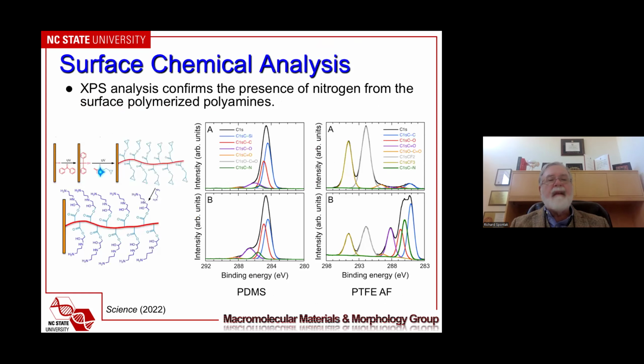This is the chemistry. I don't have a whole lot of time to go through this, but suffice it to say that it starts off with hydrogen abstraction, and then we start to grow polymer chains off of these embedded monomers. And once the polymer chains are grown, we can do a little bit of substitution chemistry to introduce the amine groups. And these are the XPS spectra to prove that, yes, we are getting nitrogen on the surface.